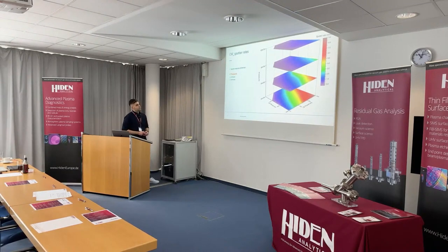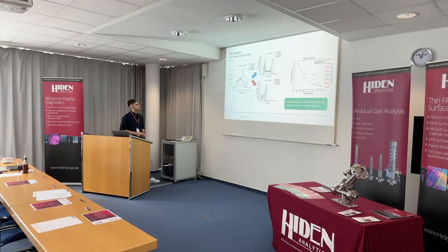So I start with pressure. Why at different pressure are the sputter rates different? This is the IDF for argon plus, 300 HF, 300 LF. You see when the pressure is increasing, the IDF integral intensity and peak energy decrease. So in LF case, when the pressure is increasing, the integral intensity at higher ion energy decreases and the integral intensity at lower ion energy increases. And in HF case, the integral intensity decreases and the peak shifts to the lower energies. So as the pressure is increasing, the average energy and the integral intensity decrease.